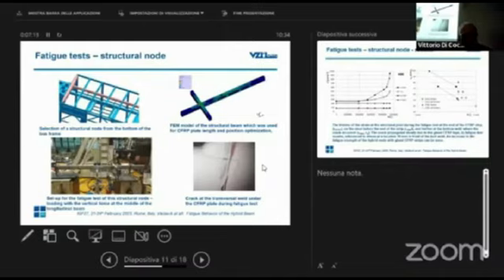Another part which we tested was the part of the structure of the bottom part of the bus. We have some support of FEM calculation where to put the CFRP plates. On the left side, on the bottom, you can see the test in our laboratory, and on the right bottom there are some cracks which appear and go under the CFRP plate, but this crack appears after a longer time than when we have the steel part without CFRP.